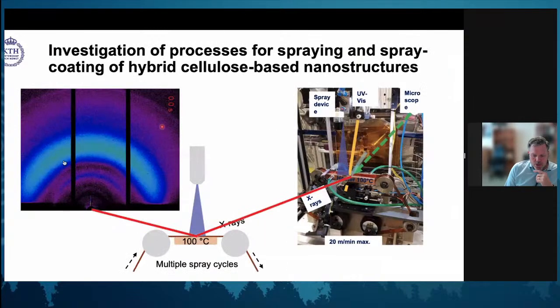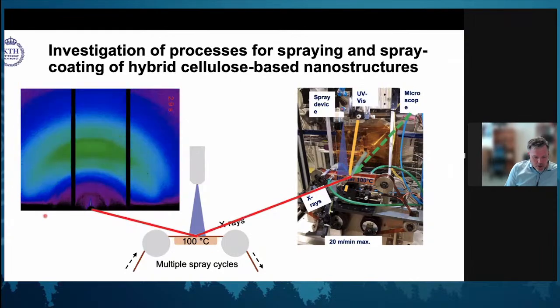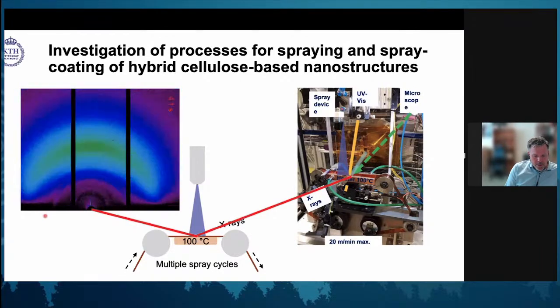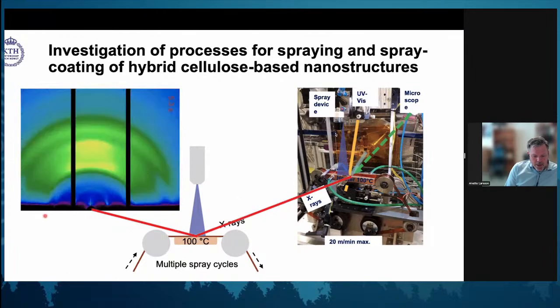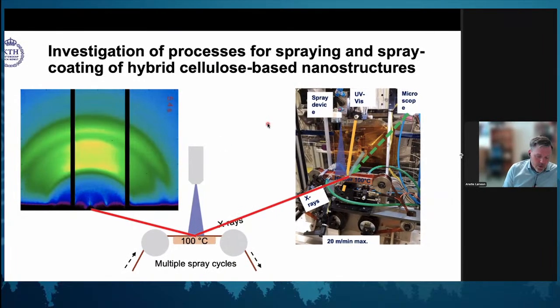And just to show a little bit of the time resolution you can achieve by doing this. So here we have the spray. We're spraying a film, and we can heat it as well. We can dry it. We can actually see dynamics. So what we'll see is a pattern that changes depending on, now we're spraying a particle with pulses, and then you can also see how this gradually then freezes and becomes a nanoparticle or a nanostructure material. So this is X-rays, and it gives you dynamics.